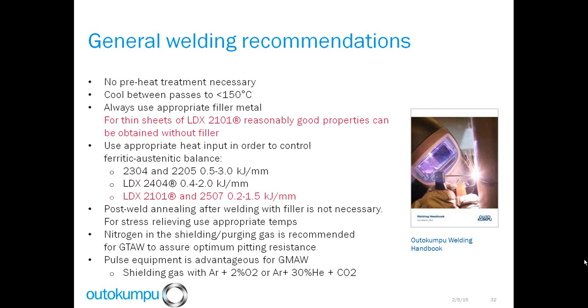Some general welding recommendations. Duplex stainless steel typically does not have to be preheated before welding. If you're looking at interpass temperatures, they generally want to be 150 degrees C maximum. Again, we want to use appropriate filler metals. Really the only duplex where you can sometimes not use a filler metal and do autogenous welding is with LDX 2101, and that's typically light gauges and a single pass weld. For the heat inputs for the various duplex stainless steels that are shown here, if we're following the correct heat inputs and we're using the right filler metals, we should not need to use a post-weld heat treatment after welding.